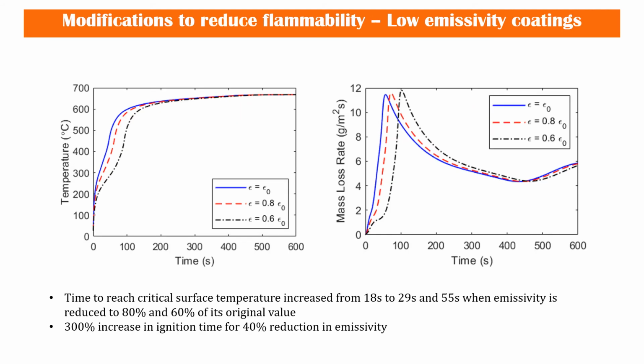The application of a low emissivity coating increased the time to reach the critical surface temperature from 18 seconds for unmodified wood to 29 and 55 seconds when the emissivity is reduced to 80% and 60% of its original value. This is an increase of 300%. Similar results were obtained for the mass loss rate.